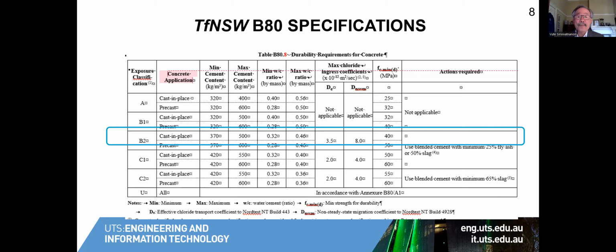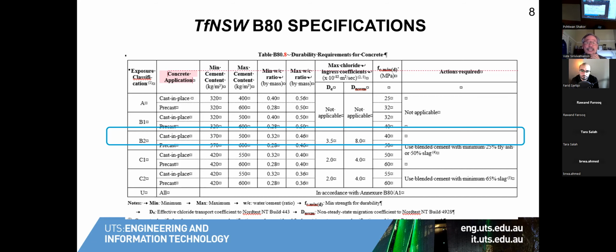Now, in this type of typical specification, we can see that there are usually prescriptive requirements. Let's look at B2 for cast-in-place type of application. There is a prescriptive requirement on the minimum and maximum cement content, and minimum and maximum water to cement ratio. It also has a performance-based requirement in terms of strength, a grade 40 MPa concrete. And because this can be used in marine exposure, there is also a requirement on the diffusion coefficient. In this example, a diffusion coefficient of 3.5 times 10 to the minus 12 meters squared per second.